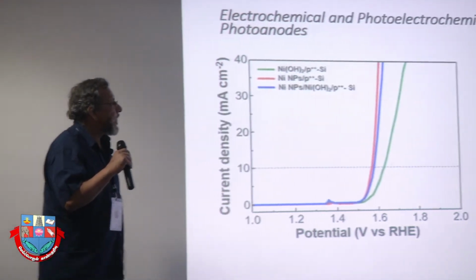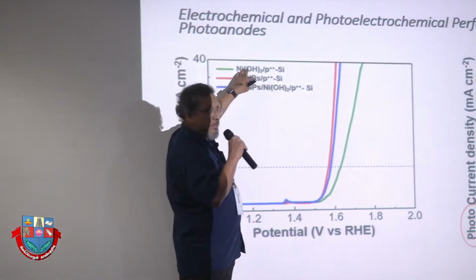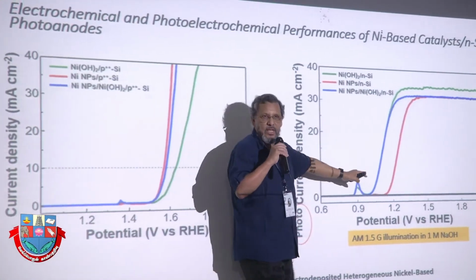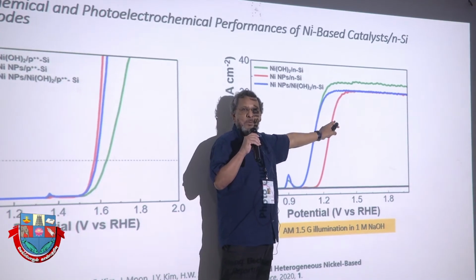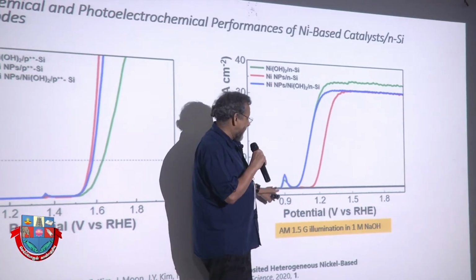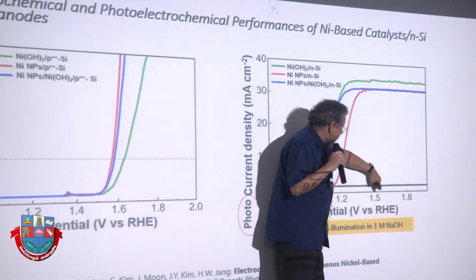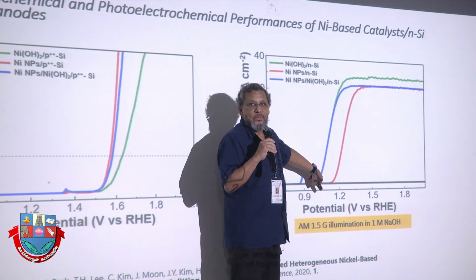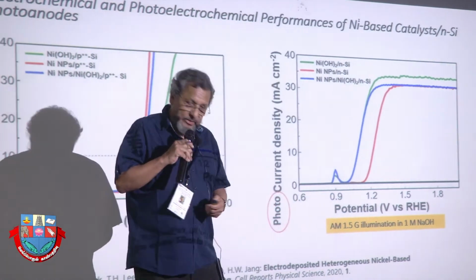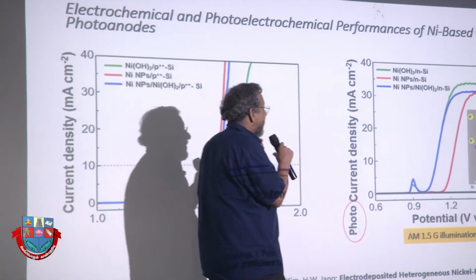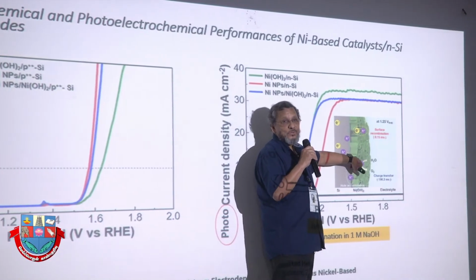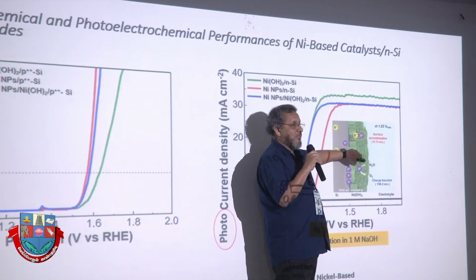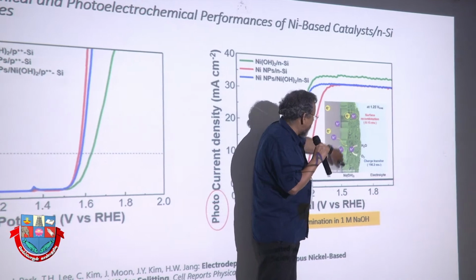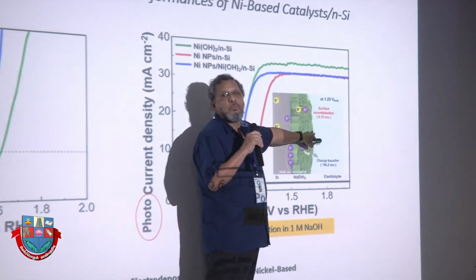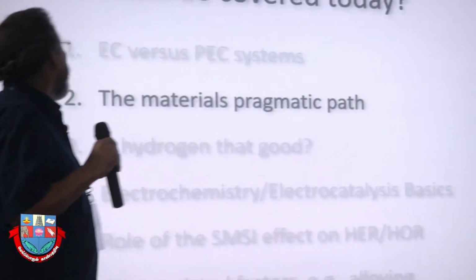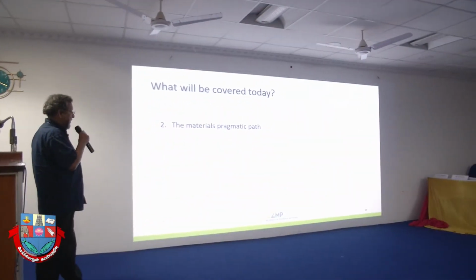All right, now, using n-type silicon, putting the same species, you observe now that this process is being carried out under illumination. So this is not a big shift, but anyway, an interesting shift, because you see that the potential which in the dark takes place is shifted by almost 1 volt. So we have here a part of the solution of the system. The important thing is that it's not only silicon. It's very important also to engineer the surface of the material. This is very important. The interfacial engineering of semiconductor material needs a way to produce this kind of layer in which the hole could be easily conveyed, of course. All right. That said, I would like to go into the materials pragmatic path.